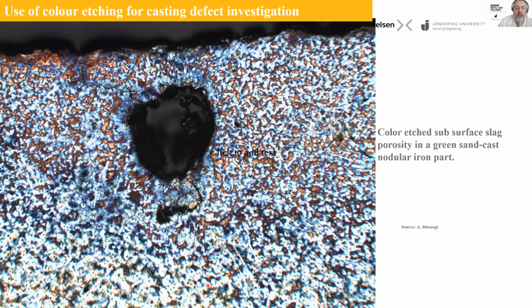Other examples are subsurface slag porosity in green sand casting. In this case, it can be seen that a bubble or gas porosity is formed, and we know that this is a slag initiated porosity because we have a tail in connection to the porosity, and the surface of the casting is along this upper surface.